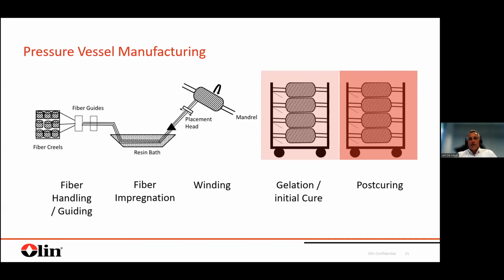Once the winding step is completed, the tanks, still with the liquid matrix, are transferred into a two-step oven process. In the first step, usually the gelation or initial cure is the target, and then in the second step, it's the so-called post-curing, the step where the full degree of cure, final Tg, and final mechanical properties are achieved. So overall, we see 4 to 5 or even 6 process steps, depending on how deep you dive in the different processes. And so overall, it looks a little bit too complex to directly guess the processing or the resin requirements based on this process.